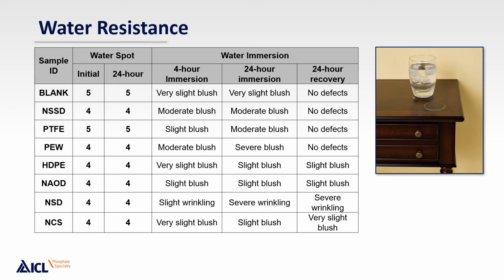Water resistance was measured in two different manners. One of them was the spot test that you just saw previously on the chemical resistance, and I just wanted to highlight it because it actually was a bit surprising to me that many of the additives actually showed a slight detriment, or I wouldn't say detriment, but a slight lower level rating than the blank control. Keep in mind that the difference between a 5 and a 4 in my scale is 5 is no effect, 4 is just a very slight ring that is visible basically at the border of the watch glass.